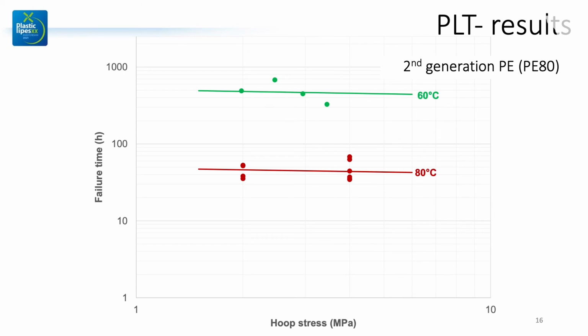But of course then the pipe owners asked, okay, that was the really old generation polyethylene pipe. What about the second generation? So the PE80, the high density PE80s. These pipes do have a comonomer inside, but they're not made with a two-step polymerization process. So they're not really linked to the longer polymeric chains in the material. So what about those second generation? So we tested them as well. And these are the results.